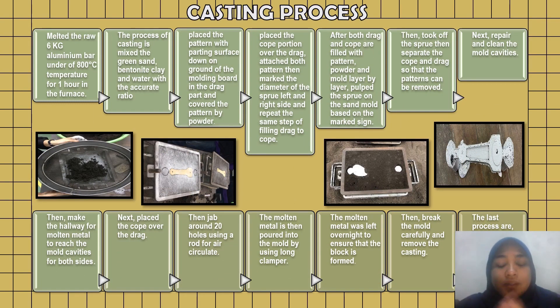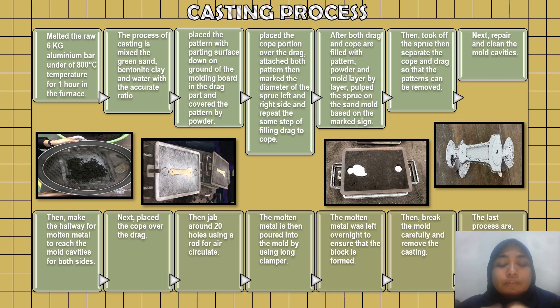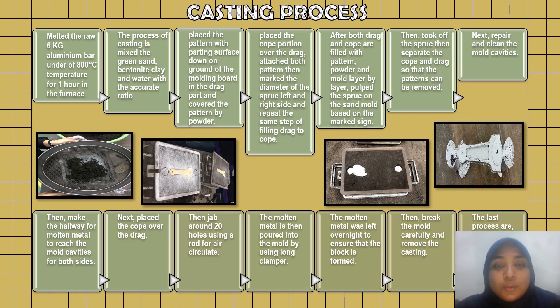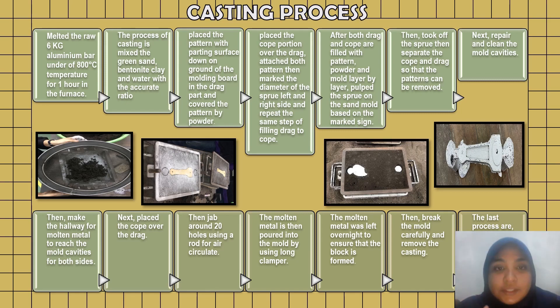Next, we proceeded to the casting process. The first step is to melt the raw aluminum bar at 800 degrees Celsius for one hour. Then we made the mold by mixing silica sand, bentonite clay, and water in accurate ratios. After that, the pattern is placed with the parting surface down on the molding board in the drag part and covered with powder.